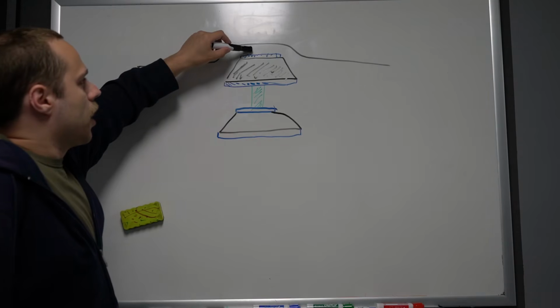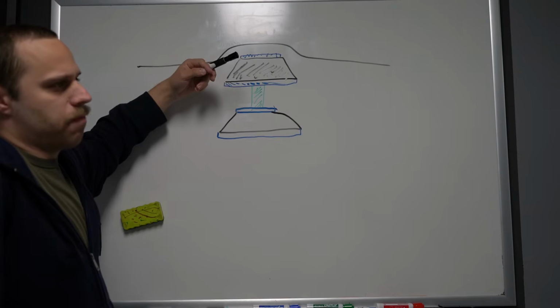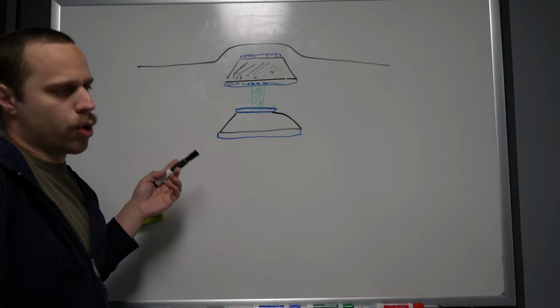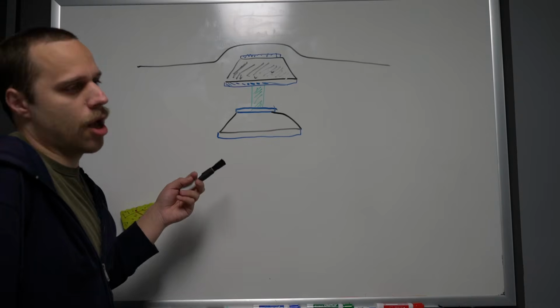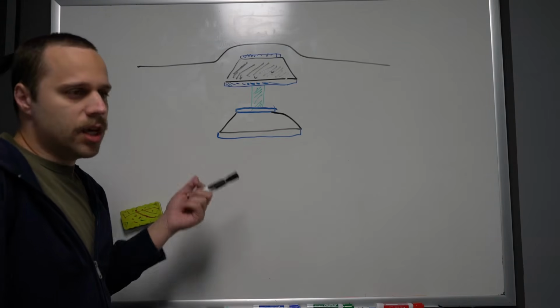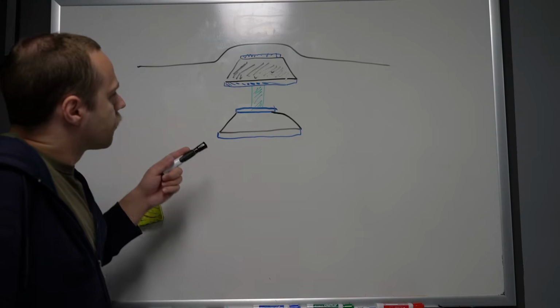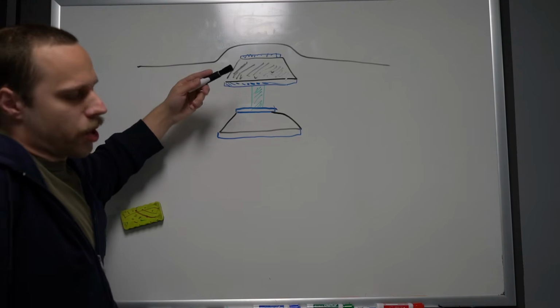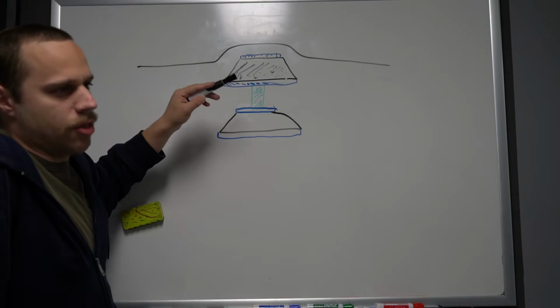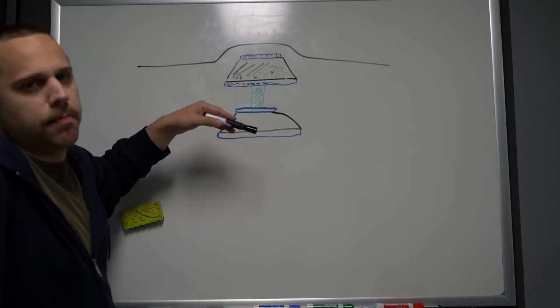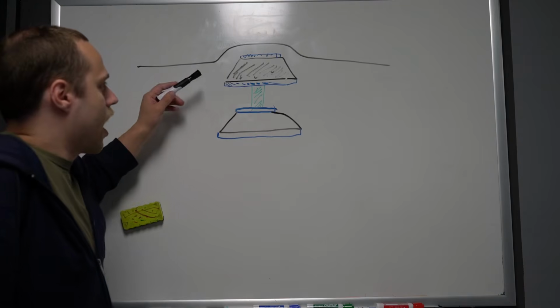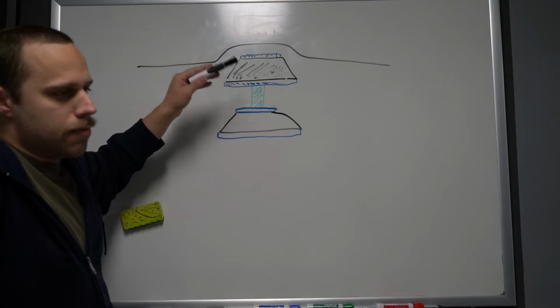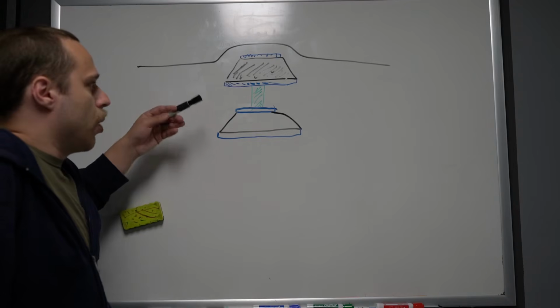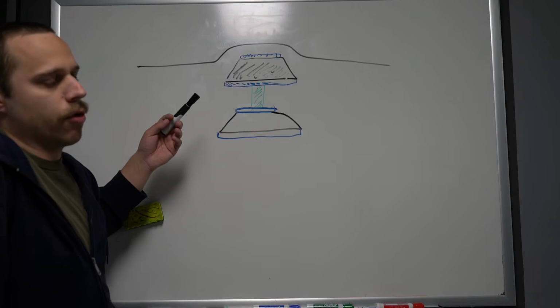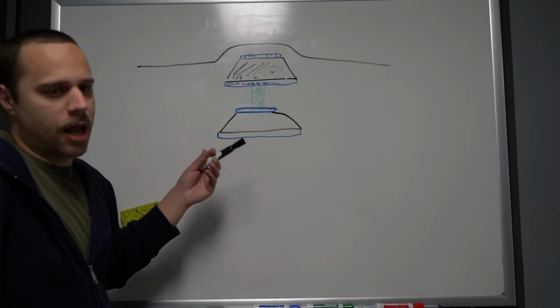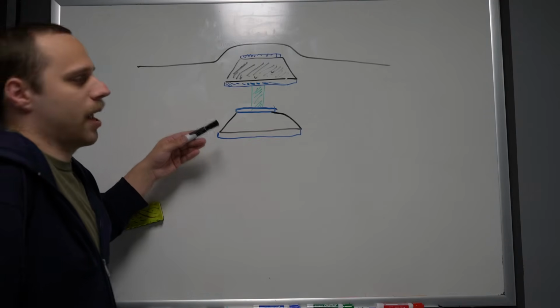So the dielectric is a silicate material. It's not pure SiO2. It's typically some sort of a CVD oxide. There could be some spin-on glass in there, but it's usually going to be CVD of silane or TEOS based. And so it's going to be a lower density, not completely solid silicate. There are going to be small voids, and it's not a monocrystalline fused quartz or anything like that. But for chemistry purposes, we can mostly treat it as just glass. We're not dealing with any of the super modern stuff that is doing low-k organosilicates or any of that. This is all old school, again, 350 nanometer nodes.